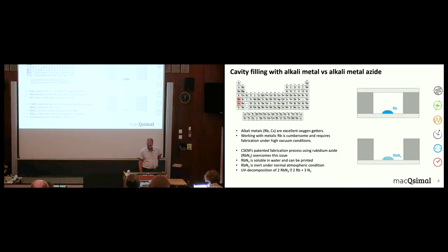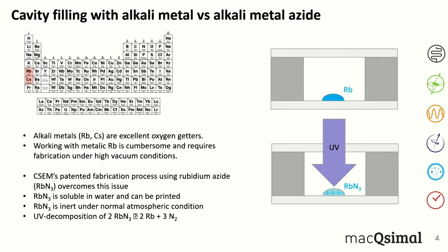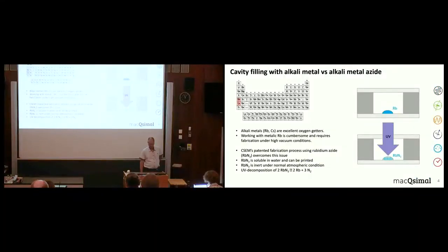Then, once we did the spotting, we close the vapor cell with a glass, and then we have to make a decomposition, which we do with UV irradiation. Upon this decomposition, we decompose the rubidium azide into metallic rubidium and nitrogen. And the nice thing about this process is that, at least in some applications, these vapor cells need a buffer gas inside, and in many cases the buffer gas is composed of nitrogen and argon. So in this case, we do the bonding at the end, where we close the cell under argon atmosphere, and we have the nitrogen which is created in situ upon decomposition. For this way to fabricate the vapor cells, we also have a patent that was granted.